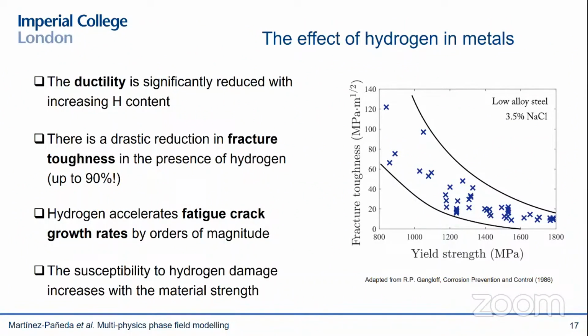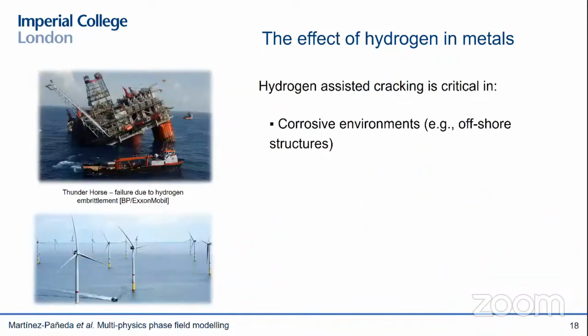So this is quite important because it's basically telling us two things. The first one is that hydrogen is compromising decades of metallurgical research. So we have developed high performance materials, but we cannot use them. And the second one is that by using these modern high strength steels, we're very significantly widening the range of environments where hydrogen is problematic. Very little hydrogen content is sufficient to trigger hydrogen-assisted failures in many applications and sectors where we never heard about this problem before. So hydrogen embrittlement has traditionally been a problem related to offshore structures, where we have very aggressive environments.